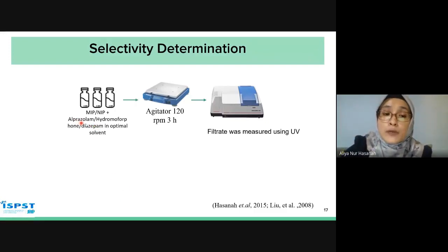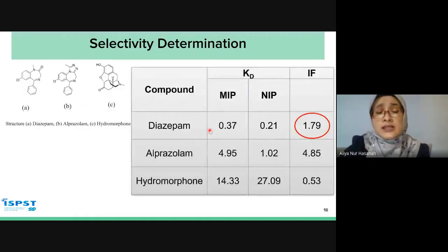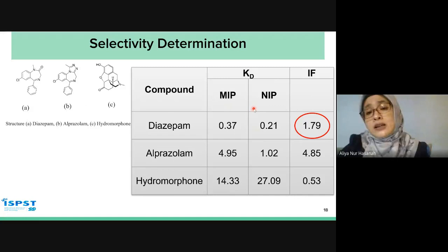using compounds that have a similar structure to diazepam, which are alprazolam and hydromorphone. We mix them with the MIP or NIP, and then agitate also at 120 RPM for 3 hours, and the filtrate was measured using UV. From this determination, we found that the distribution constant of MIP is larger than NIP for diazepam. The imprinting factor is also larger than 1, so it means the template imprinting is really successful.